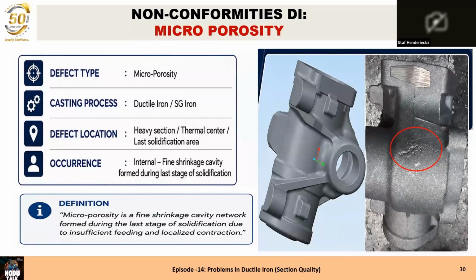How can you see this if you have, let's say, a thermal analysis curve? When you have melted your iron, you put the thermal analysis curve. If you see that the curve first drops down in temperature, then goes up a little bit and then drops down, and at the end it drops down too slowly, then that means that when the last metal is solidifying, there is no carbon anymore coming out of the liquid metal to form nodules. There will be no compensation of this type of shrinkage and it will lead to microporosity.